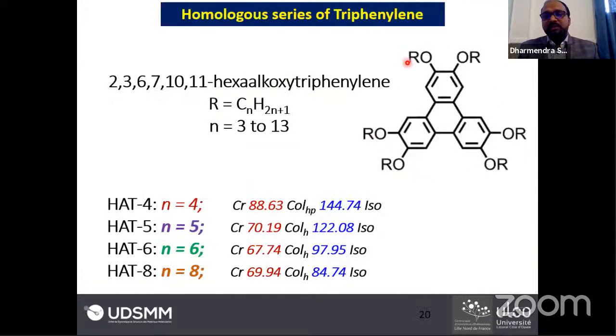So this is the chemical structure of triphenylene-based discotic liquid crystal. Here you can change the length of the alkyl chain, and you can put n equal to 3 to 13. For n = 3, they do not show the mesophase, but from n = 4 to 13 they show the mesophase. Here you can see that as you increase the alkyl chain length, the isotropic temperature